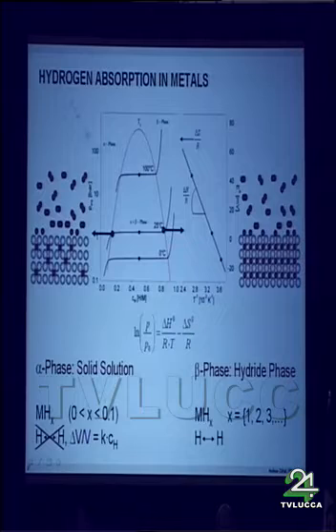We can describe the pressure-concentration relation with this Van 't Hoff equation, where the logarithm of pressure is proportional to ΔH⁰ over RT minus ΔS⁰ over R. That means the slope is given by ΔH, and the intercept is given by the entropy. Now, in most cases, the entropy change is proportional to the standard entropy of hydrogen. That is just because we are forming a solid from a gas, and the solid has almost no entropy compared to the gas, and therefore, in a first approximation, we can use the standard entropy of hydrogen as an estimate.